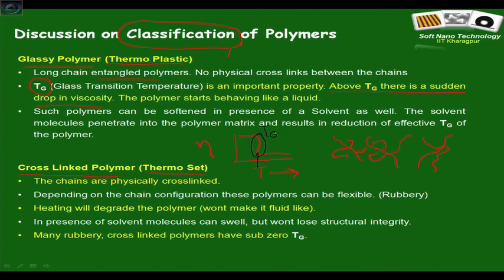This temperature corresponds to the glass transition temperature Tg. Above Tg there is a sudden drop in the viscosity of the polymer. Many polymers like polystyrene and PMMA have Tg in the range of 100 to 110 degrees centigrade. At room temperature materials made of them behave like rigid solids, and importantly they are excellent candidates for experiments — you can heat them above Tg, they behave like liquids and can be patterned, then simply bring the temperature down and the structures get frozen in as a solid, which can then be analyzed using an atomic force microscope.